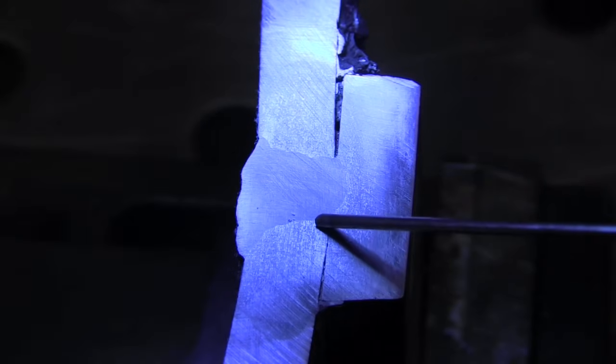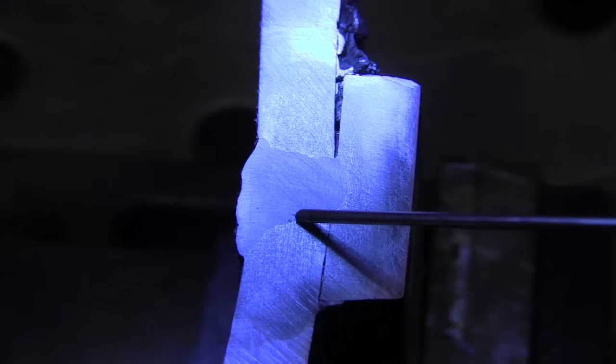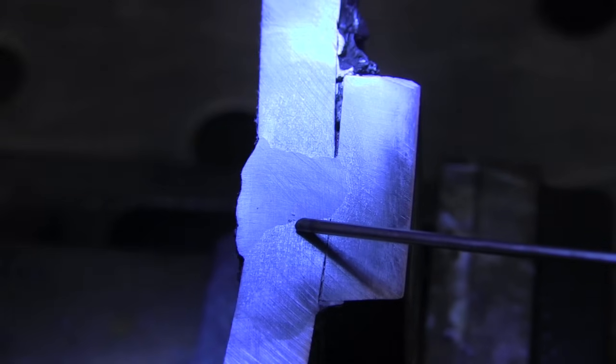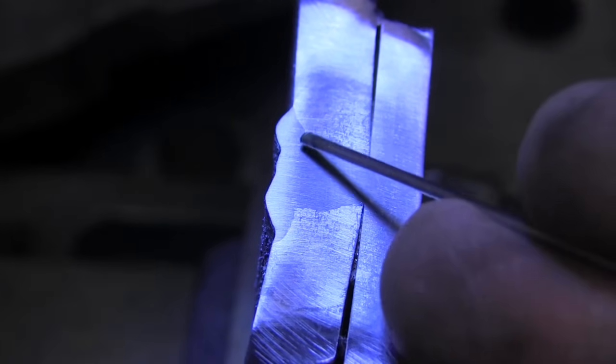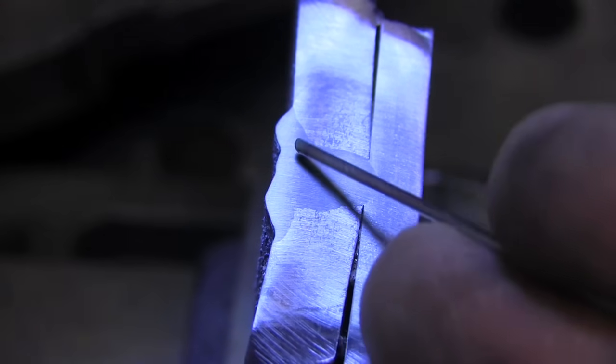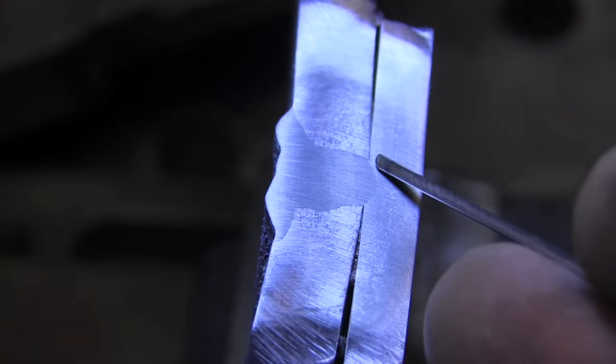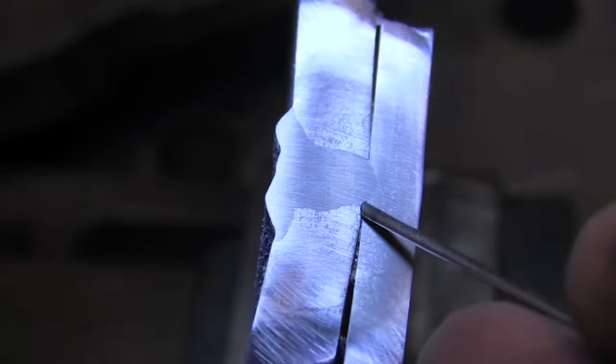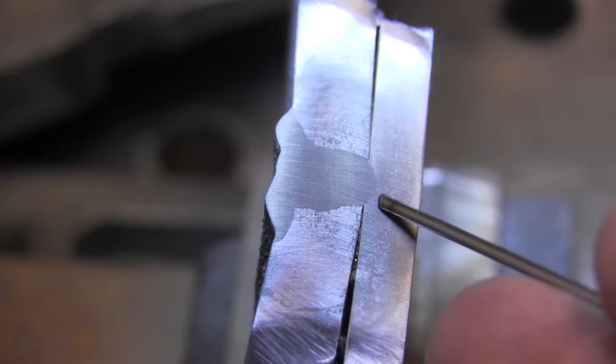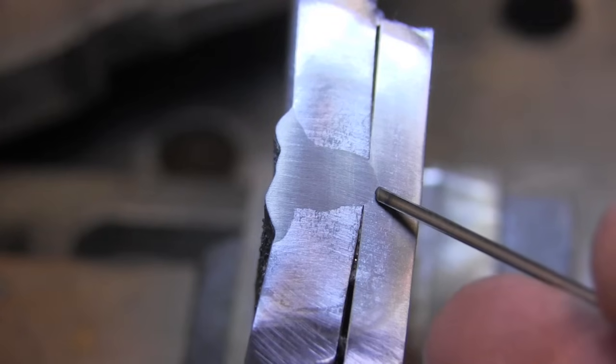I used a little thicker backing strap on here because that's just all I had laying around. But you see I have a little problem up here on the bevel, right there a little cluster of porosity and I'm going to blame that on leaving the rods out overnight without having them in an oven. But that could happen easily on a stop and start even if you've got fresh rods or rods that were in an oven. The little macro etch test here can tell you a lot. Very educational. You can see I thought I was doing pretty good but realized I went outside the bevel too far and I've got a wonky bead profile on the cap with little valleys in there and didn't penetrate as deep as I had hoped. There's nothing like a cut polish and etch right after you weld something to kind of correlate what you saw going on as far as what actually went on. Short of doing a full-blown bend test, it's a good little educational exercise.